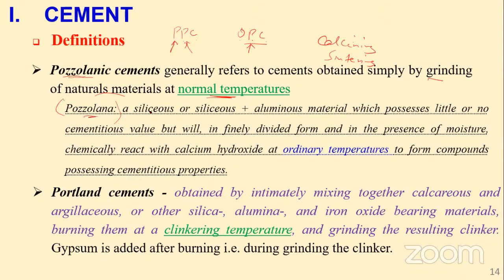Technical definition of pozzolana: it is a siliceous material. Siliceous is silica, silica oxides. It contains silica and alumina. Naturally, they possess very little or no cementitious value. And remember what is cementitious value? It has adhesive and cohesive properties. So in their naturally occurring form, they contain very little or no cementitious value. But if we grind them to a finely divided form, a very fine powder, then in the presence of moisture, they can chemically react with calcium hydroxide at ordinary temperatures to form compounds possessing cementitious properties.